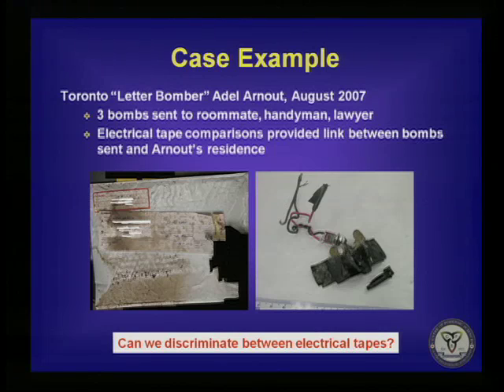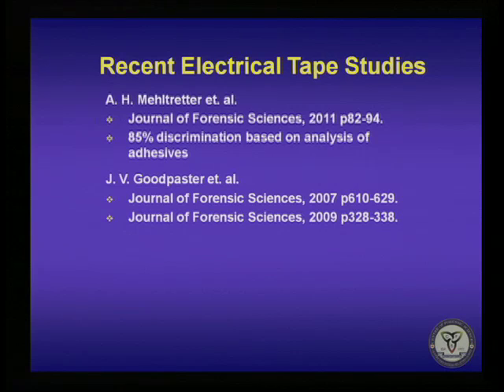One of the questions that came up in the preliminary hearing in this case was our ability to distinguish between black electrical tapes. This is when we decided to do a study of our own to see how much discrimination we can get. I do want to mention some recent studies that have been published. One by the FBI, where they found that they could discriminate. They had an 85% discrimination based on the adhesives of electrical tapes alone, with further discrimination looking at their backings. And Goodpaster has published studies looking at the discrimination based on surface features, SEM, EDX, and FTIR.